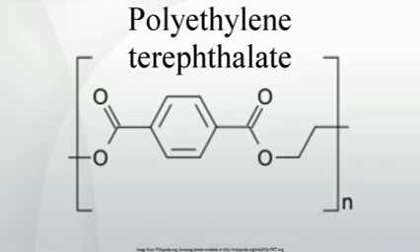Accumulation of gels and long-chain branching defects, number, concentration, and variety of non-polymer identical organic and inorganic foreign substances are increasing. With every new thermal stress, the organic foreign substances will react by decomposition. This is causing the liberation of further degradation supporting substances and coloring substances.